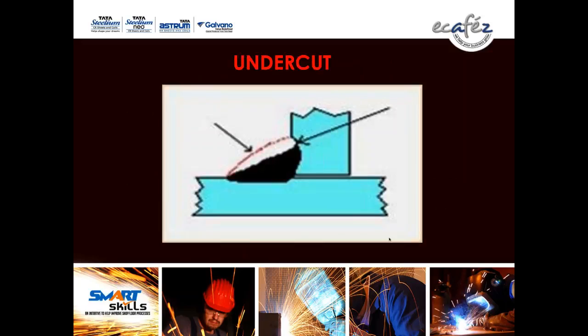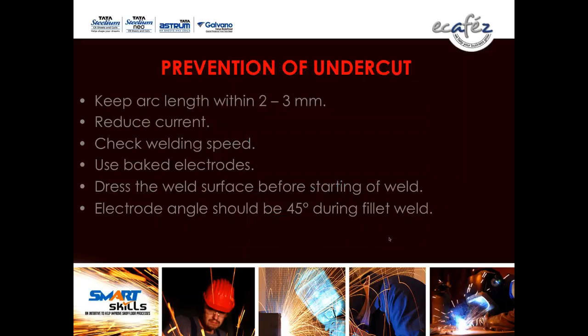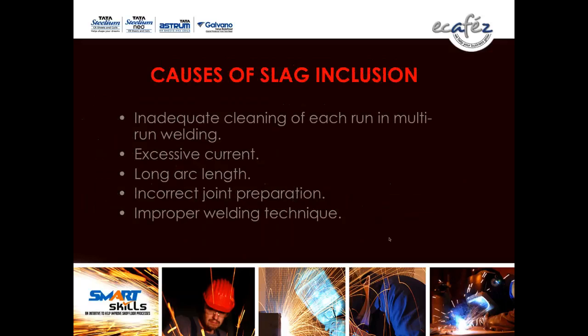Check the pictorial view. On the vertical member, there is an undercut. Prevention of undercut. Keep arc length within 2 to 3 mm. Reduce current. Check welding speed. Use baked electrodes. Dress the weld surface before starting the weld. Electrode angle should be 45 degrees during fillet weld.